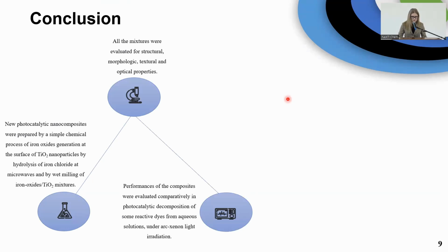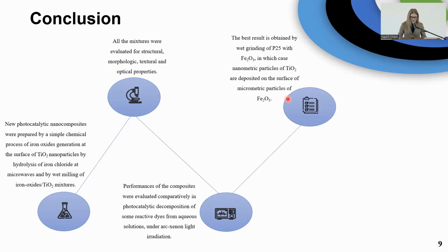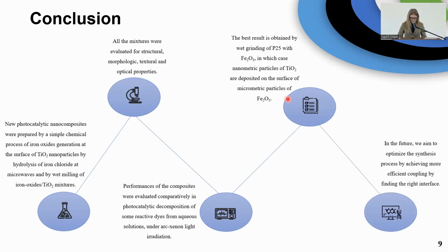Performance of the composites was evaluated comparatively in photocatalytic degradation of some reactive dyes from aqueous solutions under arc-xenon light irradiation. The best result is obtained by wet grinding of titanium dioxide with iron oxide, in which case nanometric particles of titanium dioxide are deposed on the surface of micrometric particles of iron oxide.